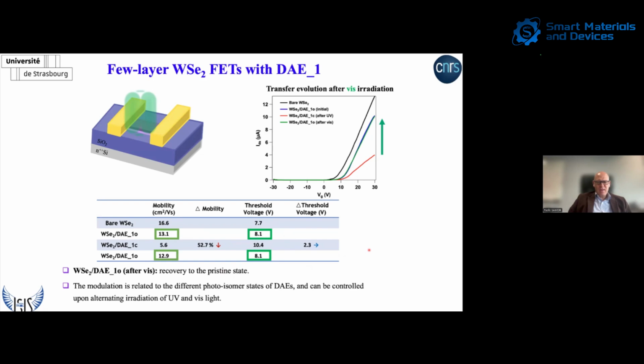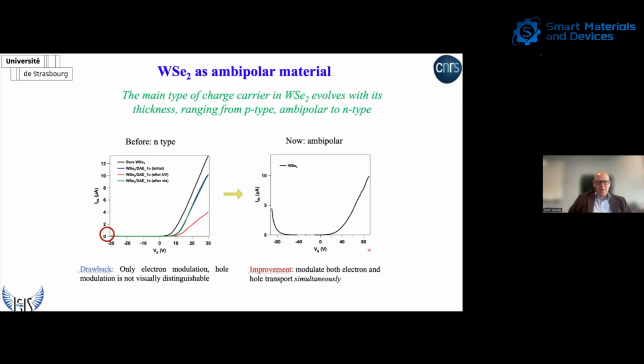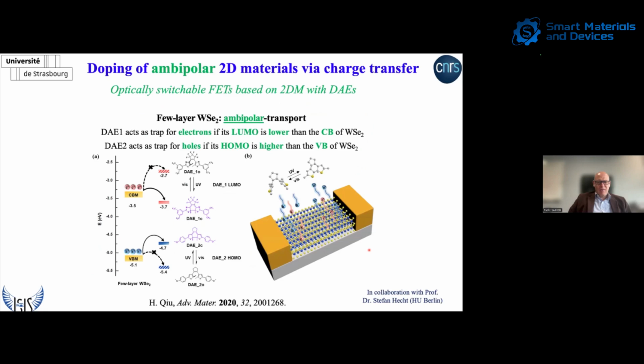Now, as I mentioned, one characteristic of tungsten diselenide is that, depending on the thickness, it can also behave as an ambipolar material. And so that is what we have done. In this case, you have to think of doing something similar, but considering that you can play at the same time not only on the electron transport, but also on hole transport. So this means you have to think not only in terms of the conduction band and trapping and untrapping the electron transport, which is what we did in the previous example.